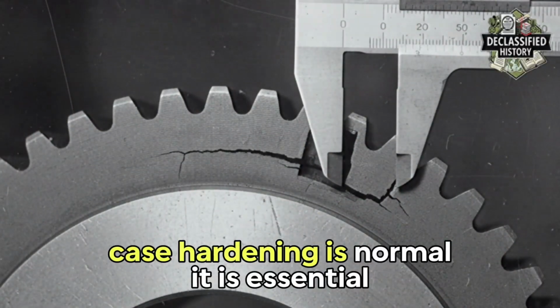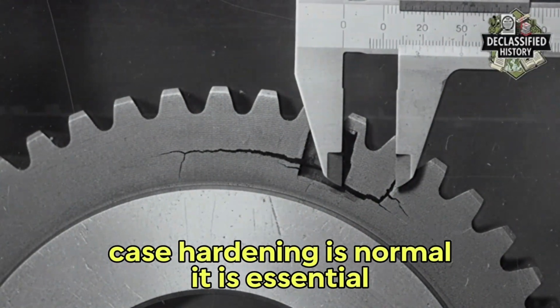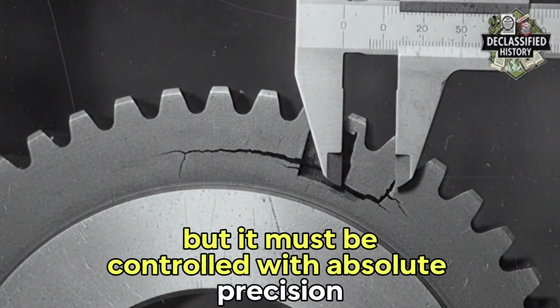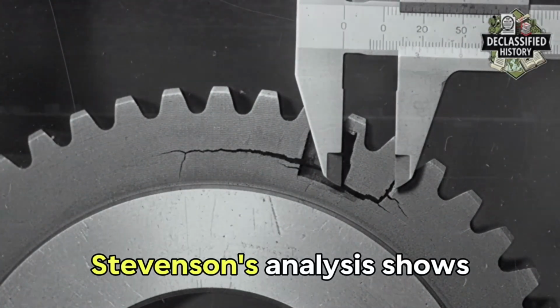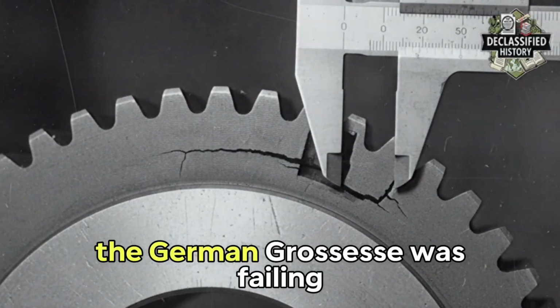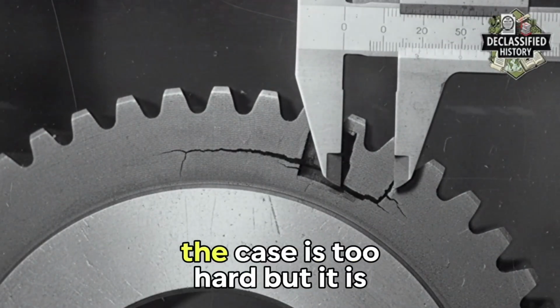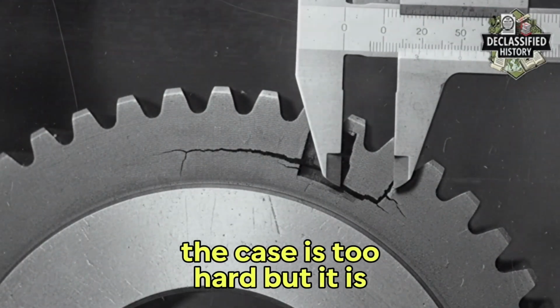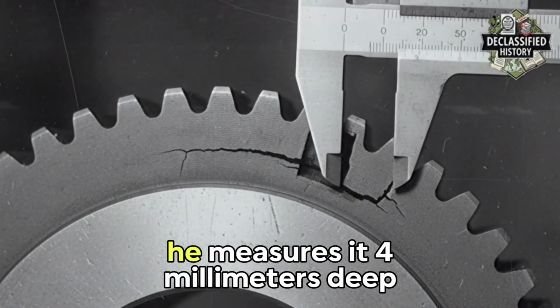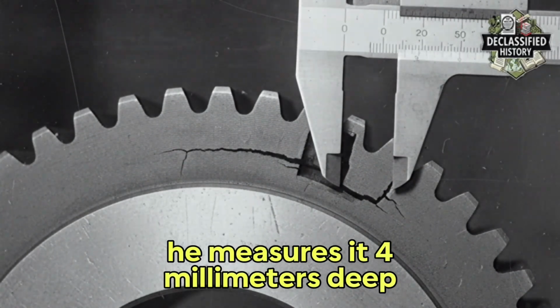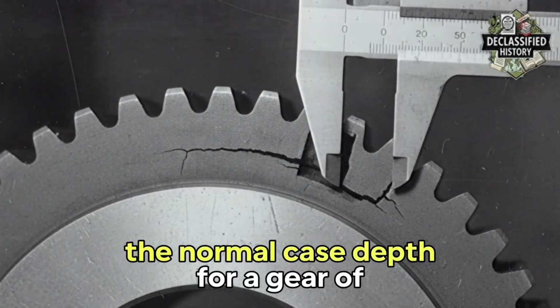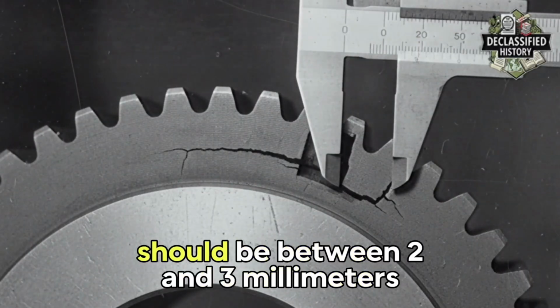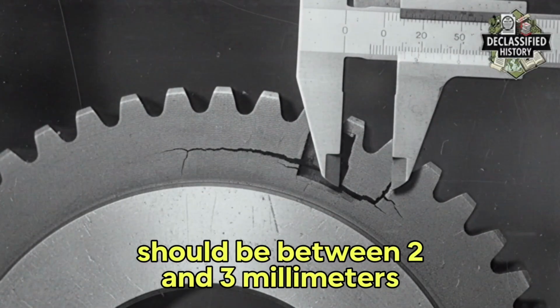Case hardening is normal. It is essential. But it must be controlled with absolute precision. Stevenson's analysis shows the German process was failing. The case is too hard, but it is also too deep. He measures it, 4 millimeters deep. The normal case depth for a gear of this size should be between 2 and 3 millimeters.